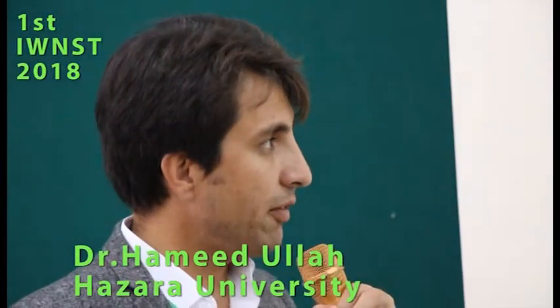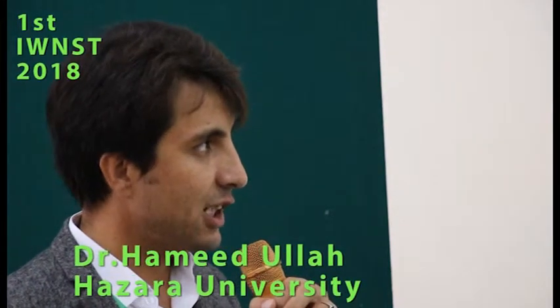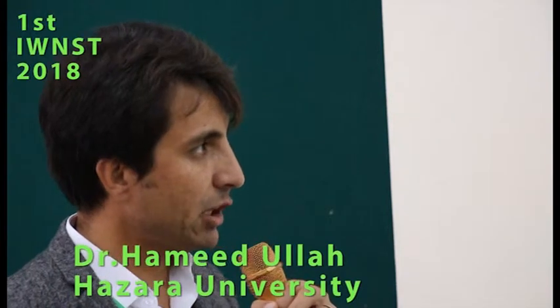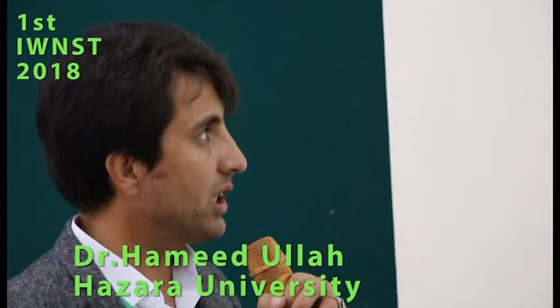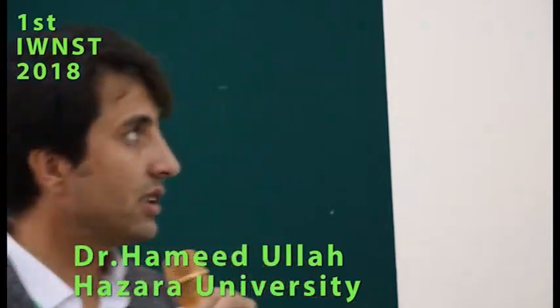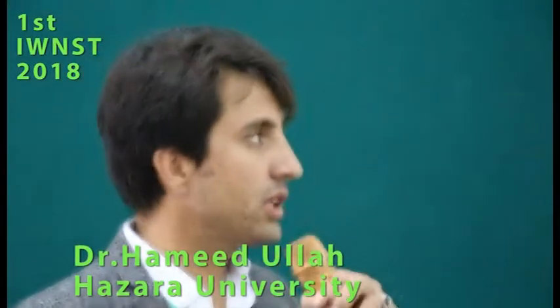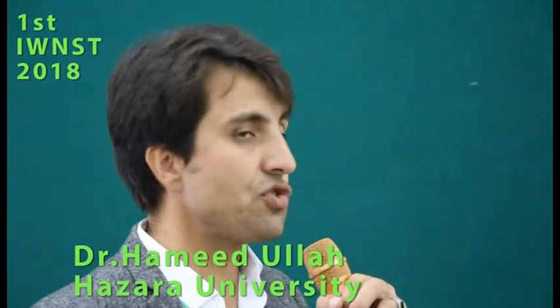And I would just skip this because I have taken the time. There are some of the SEM images that we have captured, to confirm that the hollow sphere has been obtained. So I would conclude that highly anhydrous transition metal fluoride superstructures were achieved for the very first time through this careful engineering at moderate temperature, and the nano architectures are quite viable. They are stable. They can last for a longer time.